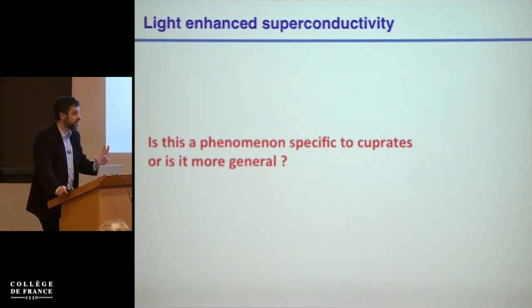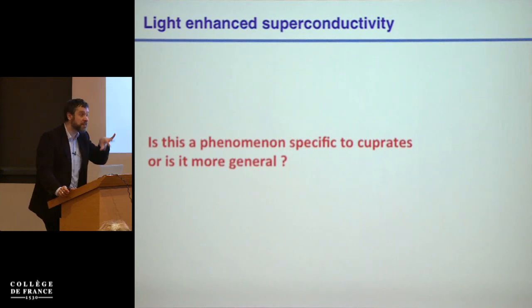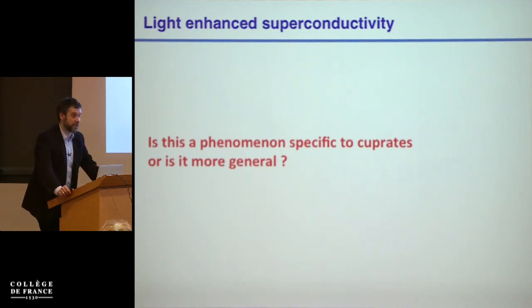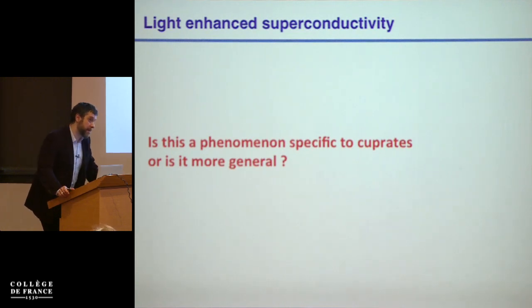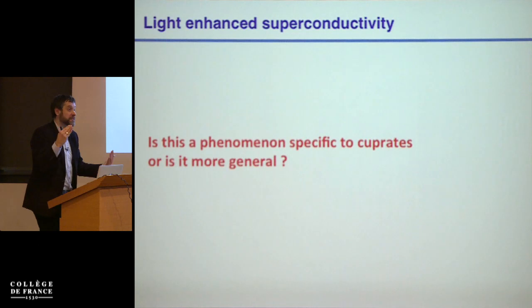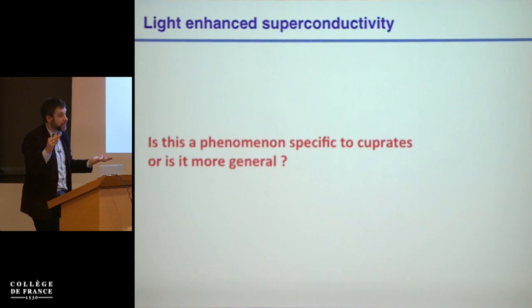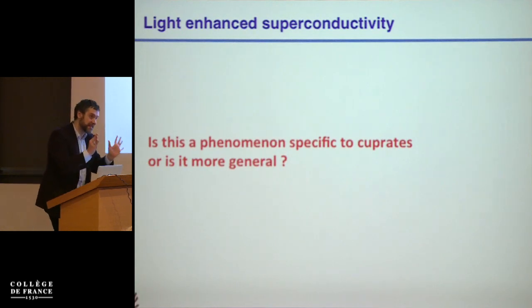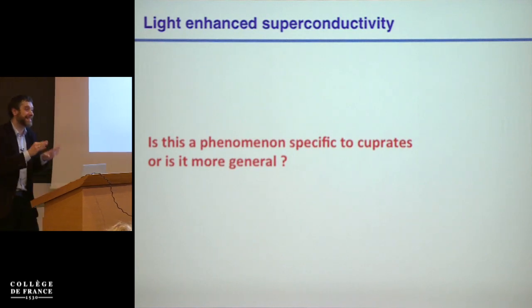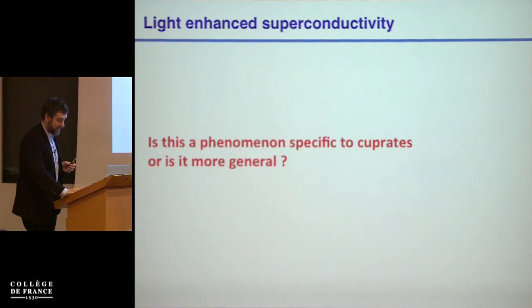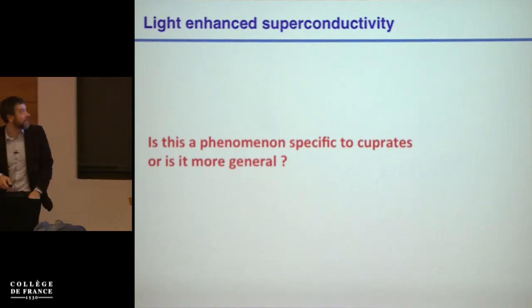And I'm not a super expert of these measurements. I'm not sure how courageously you can fit those peaks. But in principle, one could try to look at that, with the caveat that you're looking at a non-equilibrium system, and we should talk to somebody that knows about these things. The other thing is that in principle, if one could do a RIXS experiment, by looking at the dispersion of some RIXS peak with momentum, you might be able to back out, for example, if the superexchange interaction becomes stronger, then the dispersion of your RIXS peak is going to become different. So that's perhaps the crispest way to do this, provided that the experiment can be done, but there are some advances in this direction. Okay, so let's see, last topic.